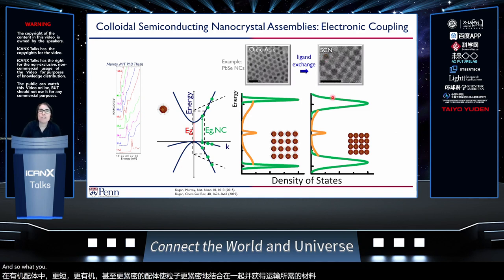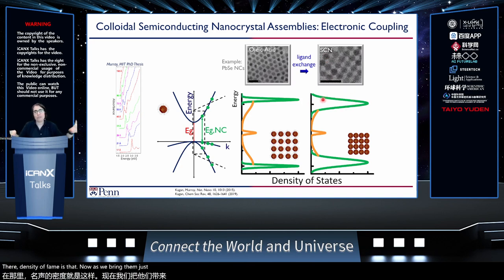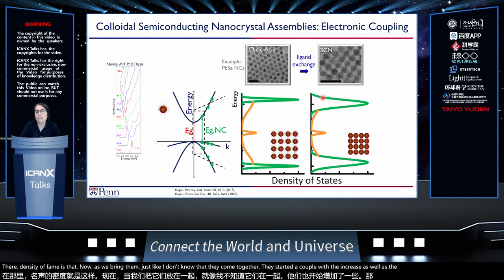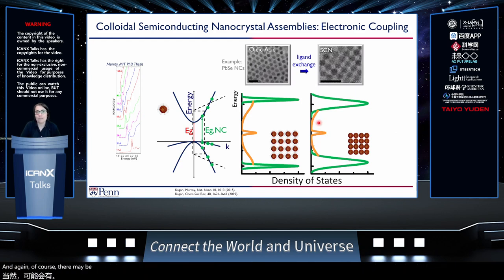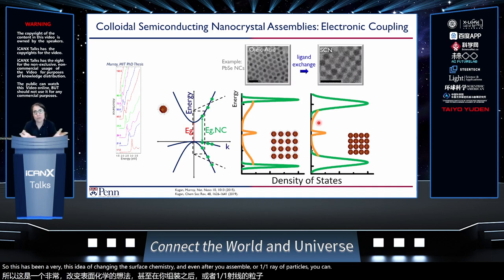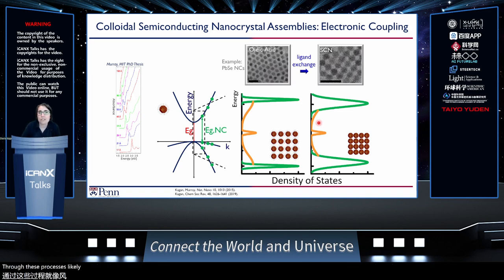And so what you can imagine in looking at their density of states is that now, just like atoms, as we bring them together, they start to couple, and we'll see an increase as well as a broadening in the density of states in the conduction and valence band. And again, of course, there may be some trap states as well. So this idea of changing the surface chemistry means that even after you assemble an array of particles, you can actually control them after their deposition through processes like ligand exchange.